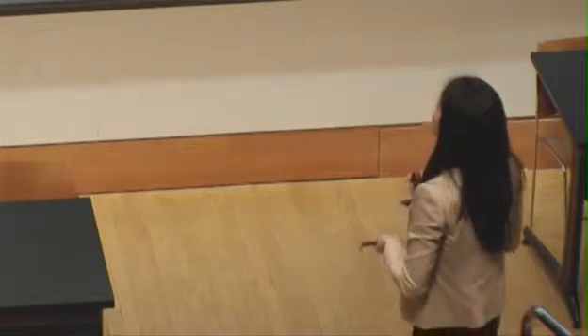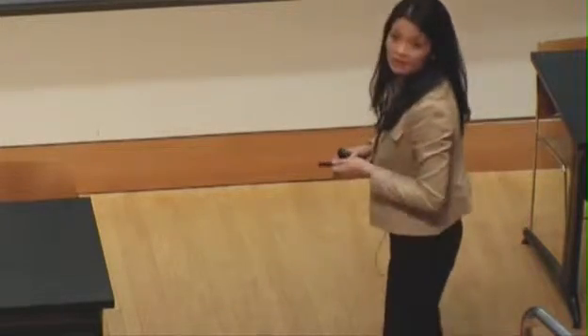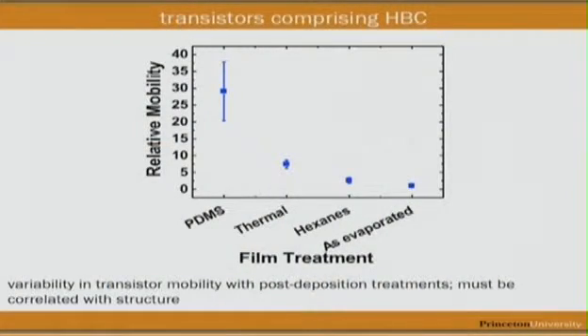So then Anna goes and makes transistors out of these films. And what she finds is as follows, right? Remember, mobility is how efficient charges are transported across that channel. If you have the as-deposited film, the mobility is low. Okay? But these three films are crystalline. Yet you'll see that their mobility is dramatically different. So this suggests that there's a difference in the structure due to the differences in processing.